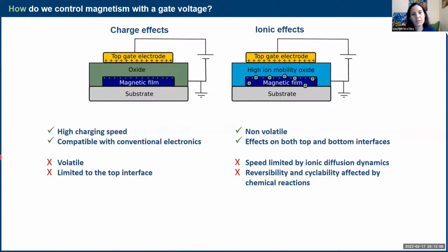So then you need it to be as close as possible as a surface, or like the materials that we use for technology in spintronics, for example, materials with perpendicular anisotropy that is seated at the top interface. But then we know that the bottom interface is also very interesting, because if you have a substrate that is a heavy metal, then you could have DMI actually coming from this interface, and you might want to control that. So this you cannot do with charge effects.